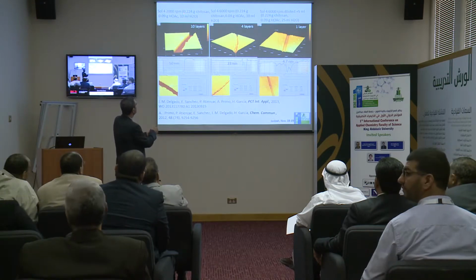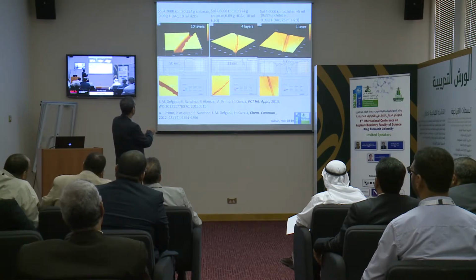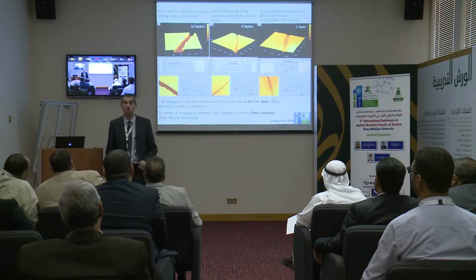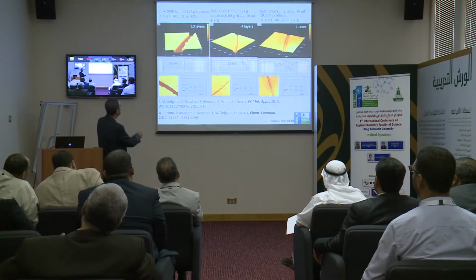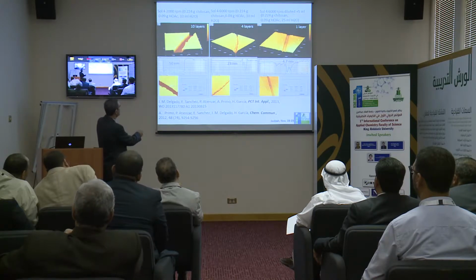In this particular case, we have chitosan, and these are the concentrations that we are using. So 200 milligrams of chitosan dissolved in this solution of water. Another thing is that we are using green solvents, so water is a good solvent for all these things. And this is the layer. And this layer has 50 nanometer thickness, so we make a cut on the film, and that allows us to measure the thickness of the layer.